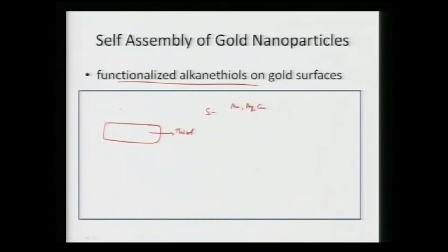And if we can make a certain structure, we can electrodeposit or sputter deposit gold in a certain pattern. So, we have a silicon layer, and over that we can provide a certain construction of gold assembly by either sputtering or any other technique, and then deposit this structure into a thiol solution. So, what we can get finally is a certain structure of gold which now has thiol attached to it with a certain functional group.